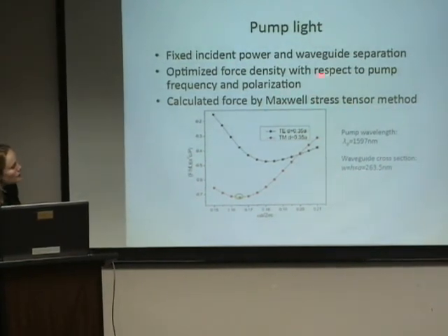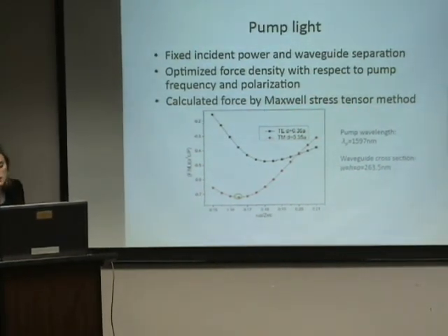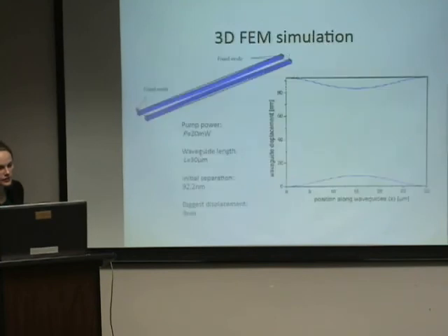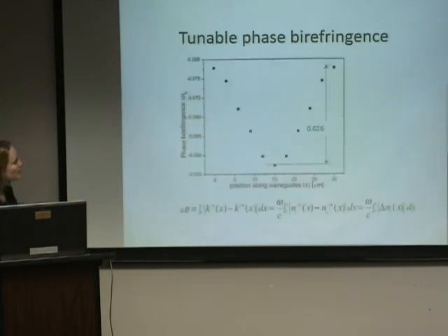So we calculate what the forces are. I'm going to skip the details in the interest of time. Then we use finite element simulations to figure out the deformations. So this is showing the displacement of the waveguide as a function of position along the waveguide. You see them deforming. Because they've deformed then, this leads to this birefringence effect. We map out what that birefringence is as a function of position along the waveguide. And we can calculate total phase shifts in the light.